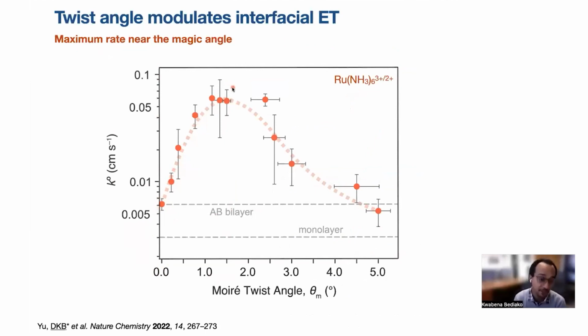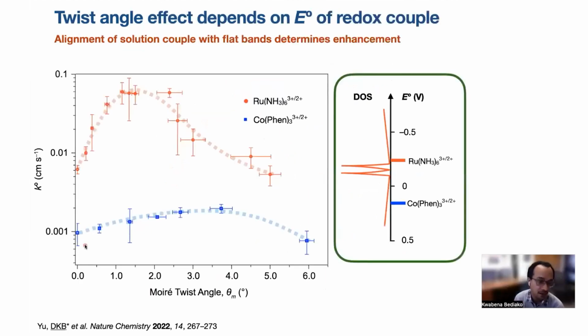We can test our hypothesis that this has something to do with the flattened bands by measuring the same electrode kinetics at another redox couple that we know is very misaligned energetically with the neutrality point, or for that matter, the flat bands of our twisted bilayer graphene. And so this cobalt 3+/2+ couple shows a much more quenched effect of the twist angle, which is in line with the fact that by the time we've applied enough potential to drive the cobalt 3+/2+ couple, we're well away from the flat bands in our Fermi level.